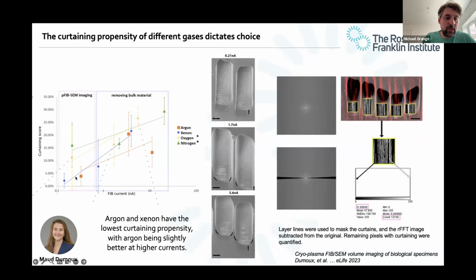And you can hopefully see at the bottom left that xenon and argon are relatively similar at low current. So low current here is 0.1 to 0.2 nanoamp. But you can see as this goes to high currents, you have a much larger degree of curtaining. And so at the bottom left, we determined that argon is probably the best because this scale to the right is shallower. And so for making very flat surfaces, we are going with argon.